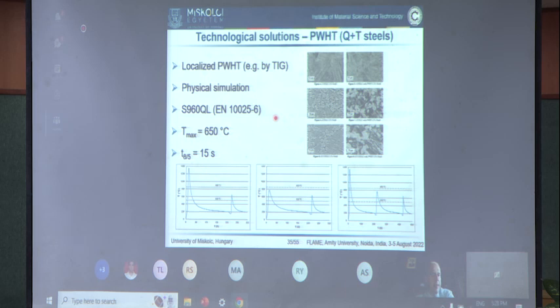During our experimental work, we analyzed the possibility of post-weld heat treating. Actually, with the Gleeble simulator, we tried to analyze what's happening in the heat affected zone if we are using a kind of tempering heat cycle. So we used a 650 degrees Celsius peak temperature tempering after the coarse-grained and the intercritically reheated coarse-grained zone.